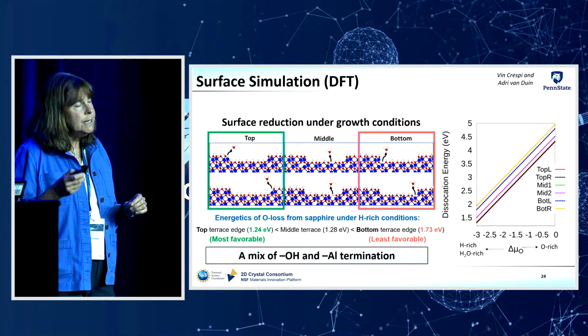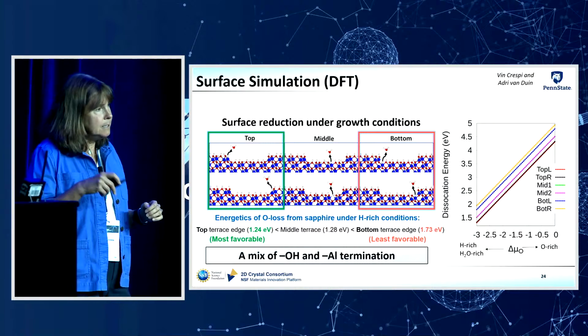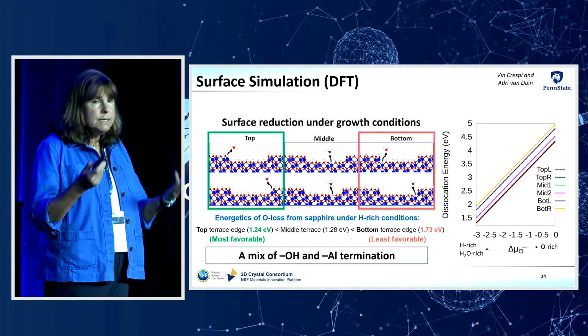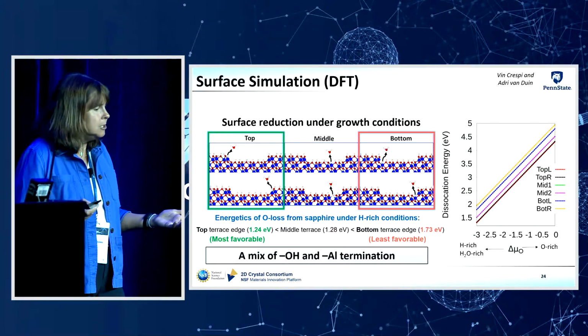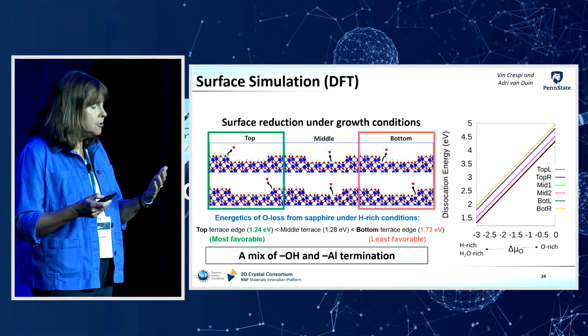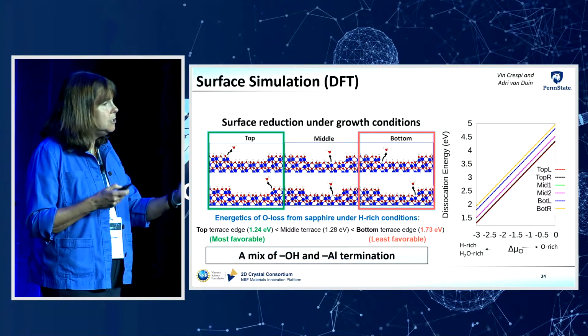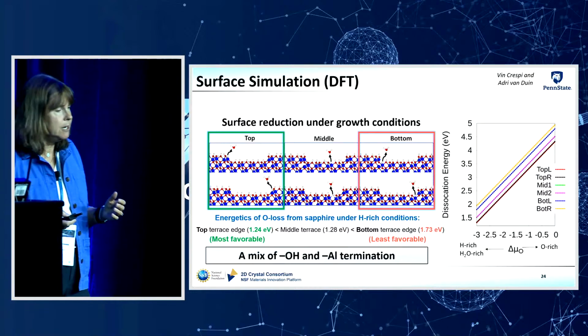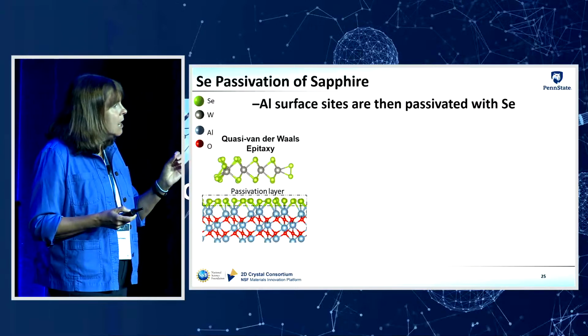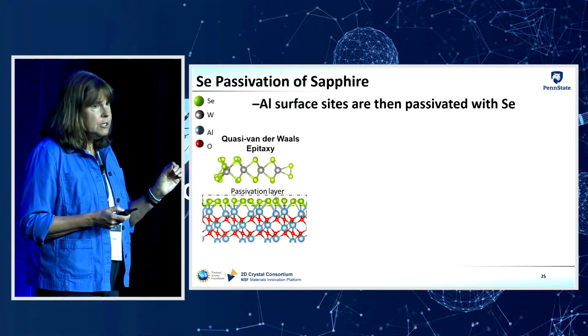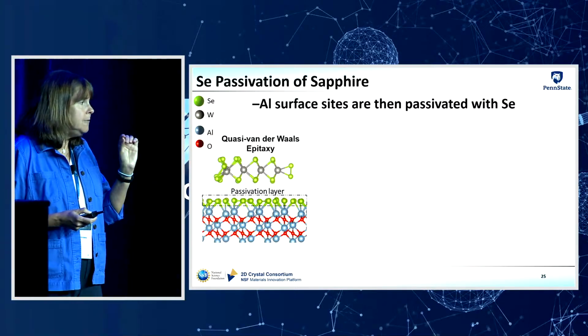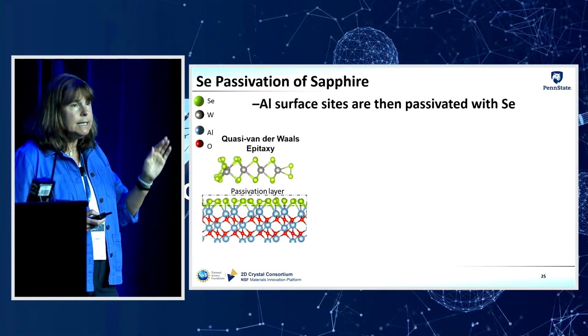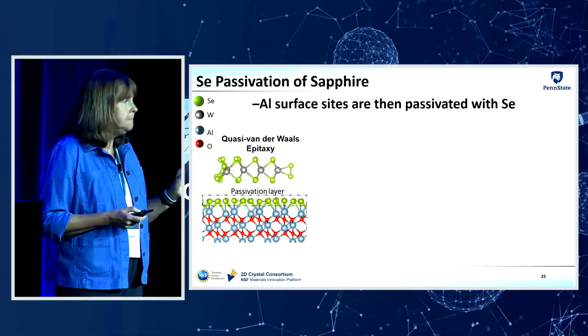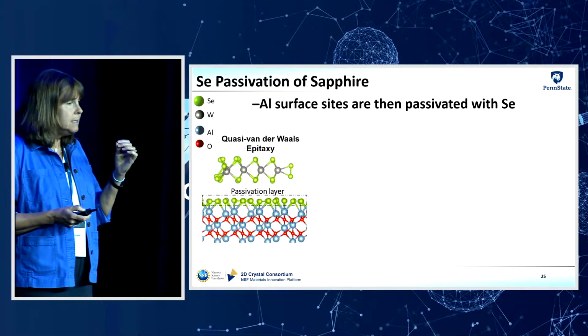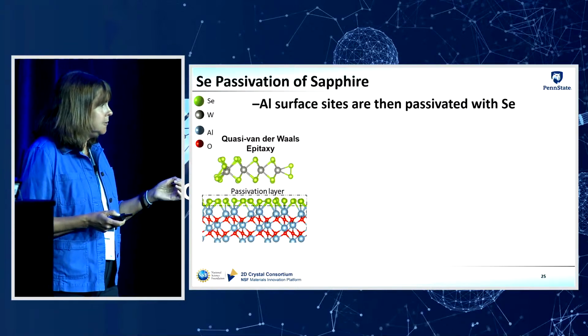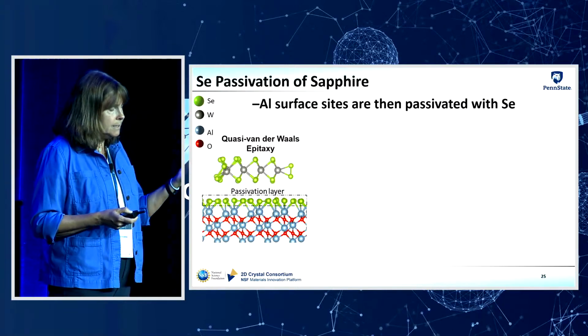And the location where it's least likely to occur is the bottom edge of the step. So this indicates that depending on the growth conditions we're using, we can have a mixture of hydroxyl termination or aluminum termination of our sapphire surface. Now, if we have aluminum termination, the aluminum atoms are going to be very reactive, particularly to selenium that's present in our growth ambient. So we would expect the aluminum terminated sapphire surface to become passivated with selenium.